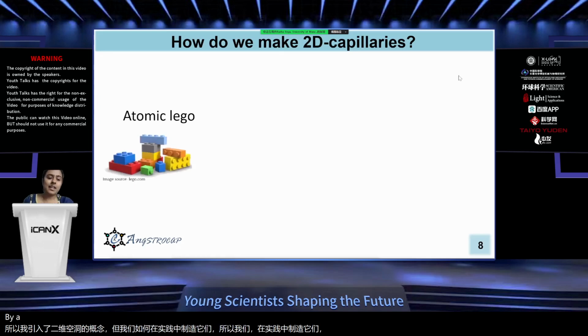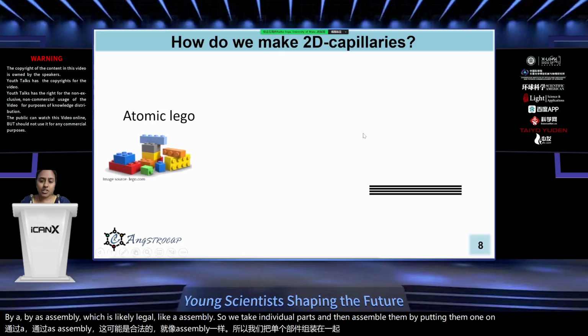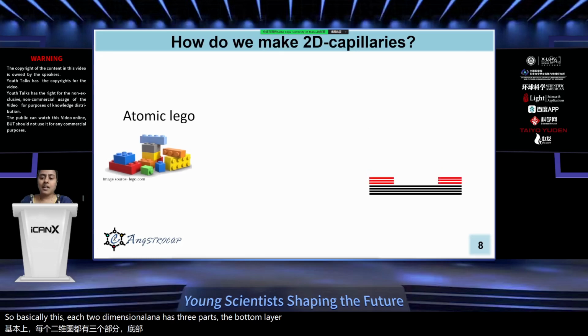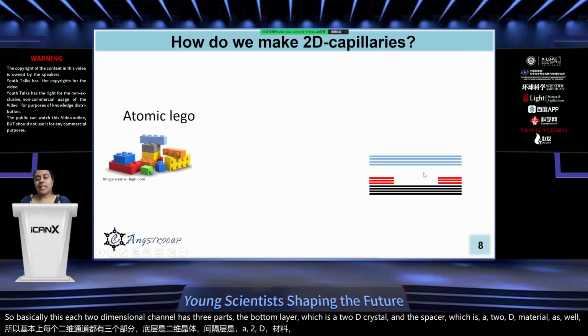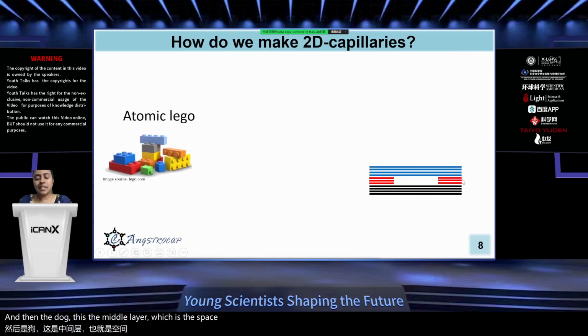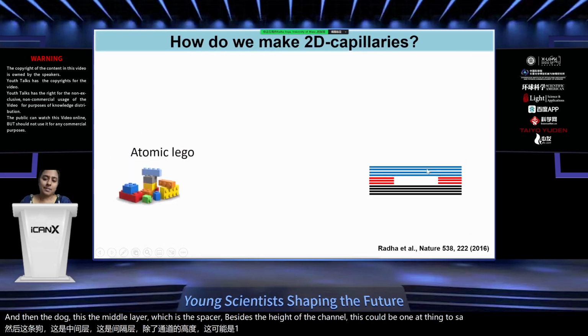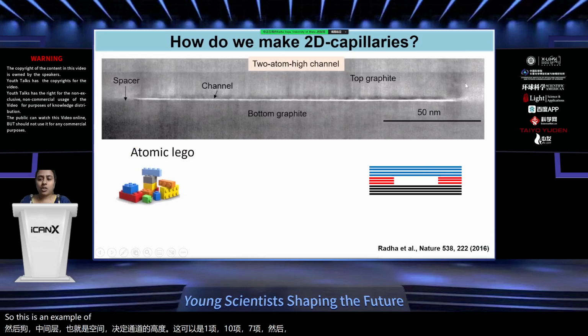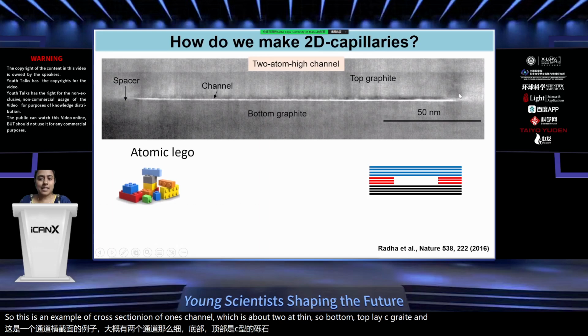We make them in practice by assembly, which is like Lego-like assembly. So we take individual parts and then assemble them by putting them one on top of each other. Basically, each two-dimensional channel has 3 parts: the bottom layer, which is a 2D crystal, and the spacer, which is a 2D material as well, and then the top. The middle layer, which is the spacer, decides the height of the channel. This could be 1 atom thin to several atoms thin. So this is an example of cross section of one such channel, which is about 2 atoms thin. So bottom and top layers are graphite, and the spacer is also graphene.